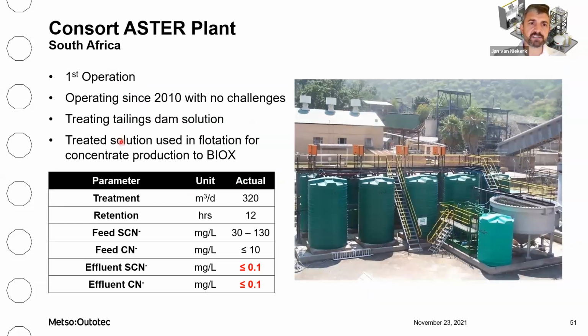The first commercialization of the technology was at the Consort plant in South Africa. Now, this is one of the plants that produces the concentrate that's treated at the Fairview BIOX plant, and therefore no cyanide or thiocyanate can be tolerated in the process water for the Consort plant. So the Aster was installed to treat tailings dam solution and allow recycling of this solution upstream to the flotation section. It's a relatively small plant, treating only about 320 cubic meters per day of solution at relatively low feed thiocyanate concentrations, but achieving very good results. And it really showed the simplicity of the process.